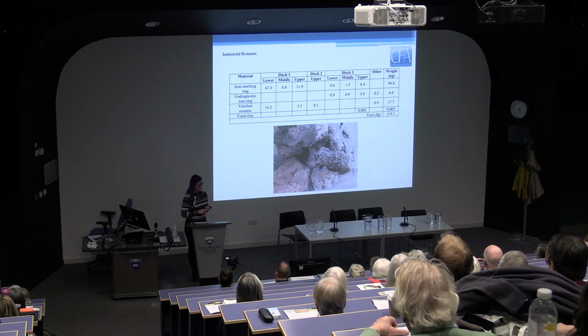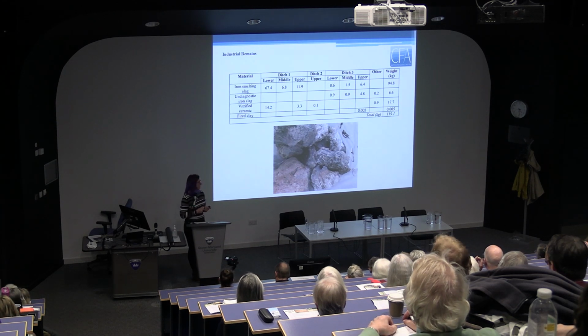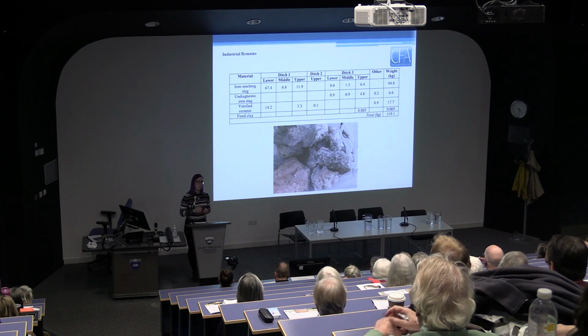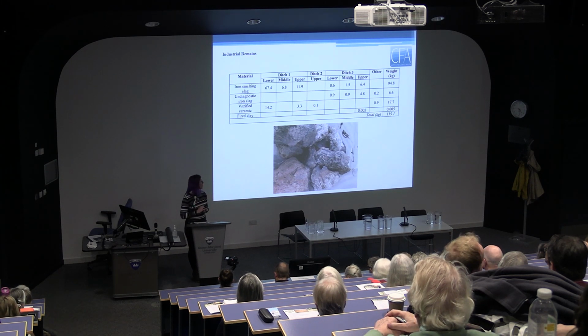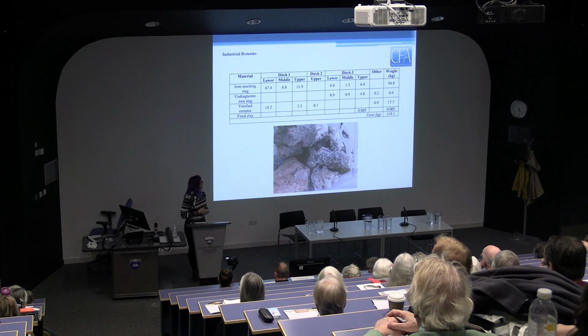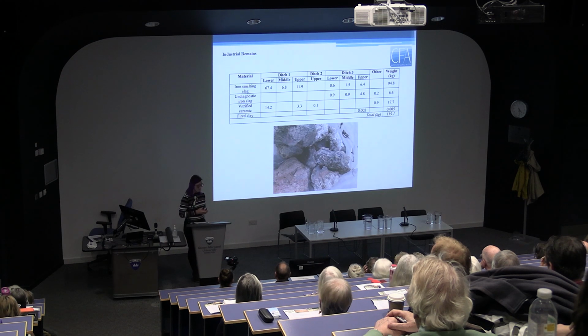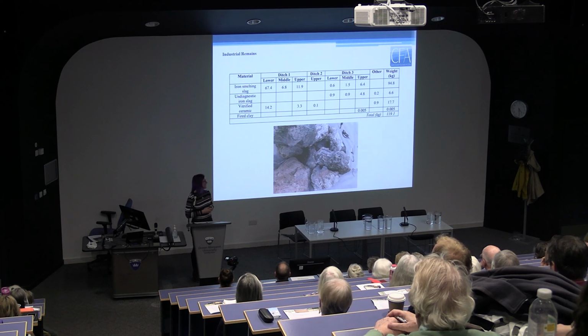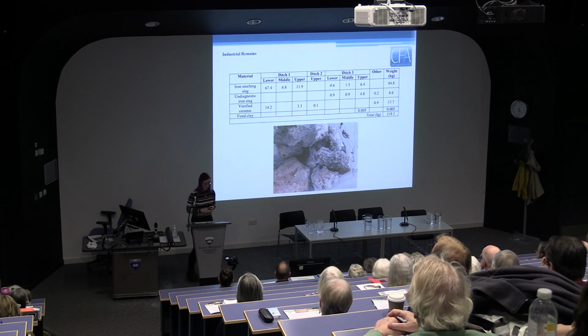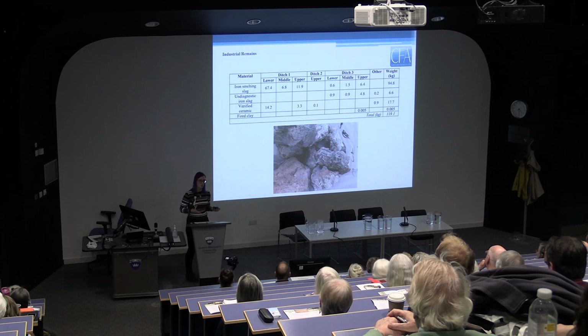Many of the pieces have vitrified ceramic and heat-affected soil still adhering, so they were in contact with the furnace walls and on the ground while they were still hot. Speaking of furnaces, the other main material that was recovered is vitrified ceramic. Some pieces of this still had slag adhered to them, and it's likely that this comes from smelting furnace walls. So even though we don't have the furnaces, we do have suggestions of their structures in the material recovered.